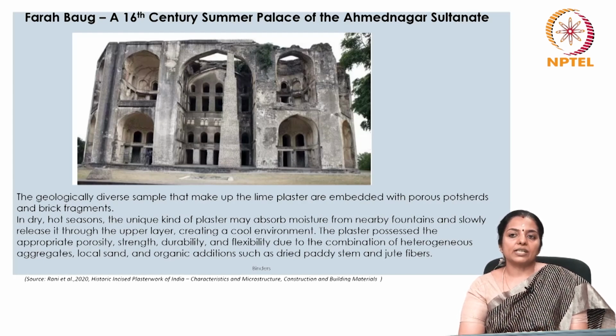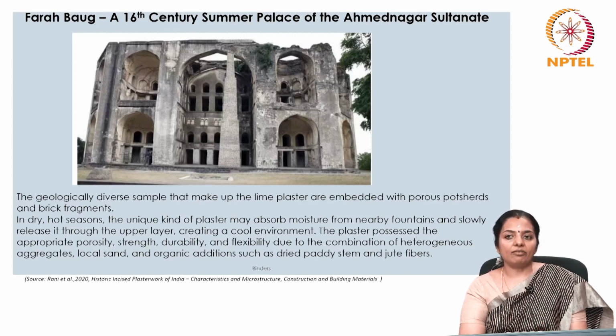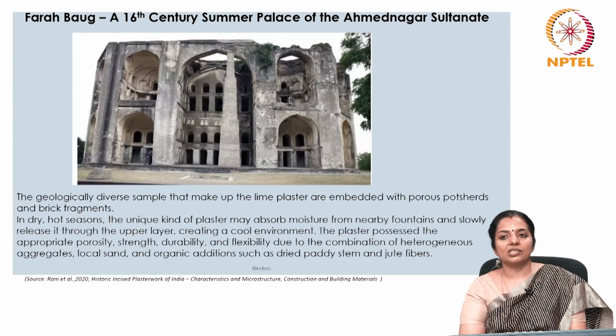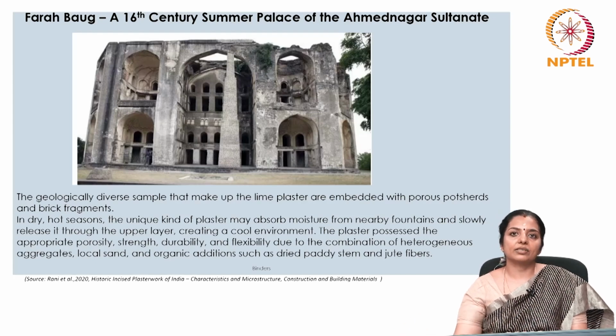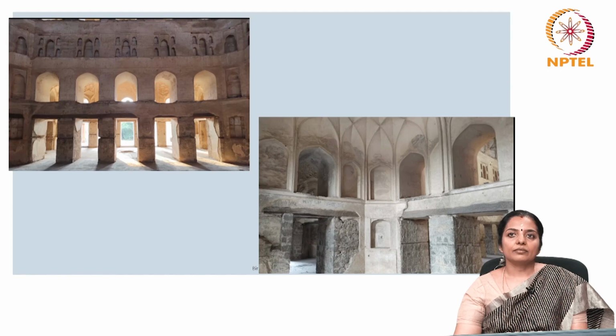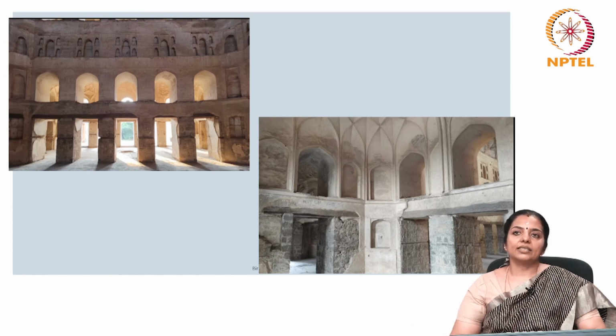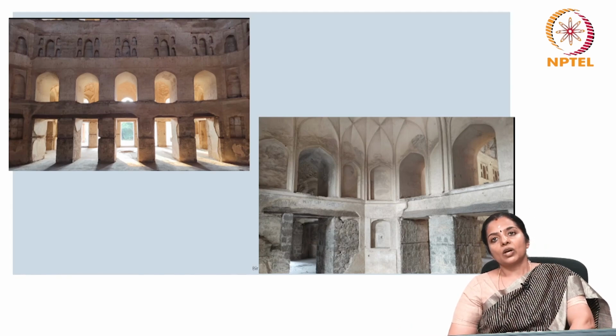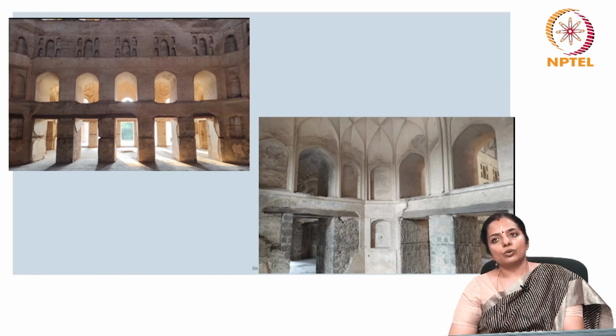So, the plaster possessed the appropriate porosity, strength, durability and flexibility due to the combination of heterogeneous aggregates, local sand and organic additions such as dry paddy stem and jute fibers. So, the natural cooling techniques used in this building, because it had used lime, kept the temperature inside the building 8 to 12 degrees Celsius lower than the outside temperature, which went even up to 46 degrees centigrade.